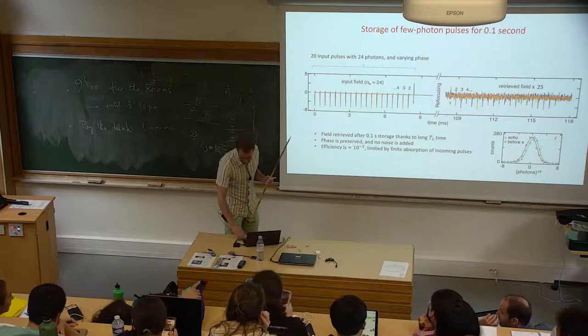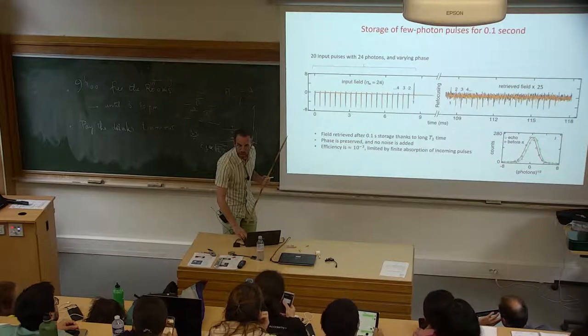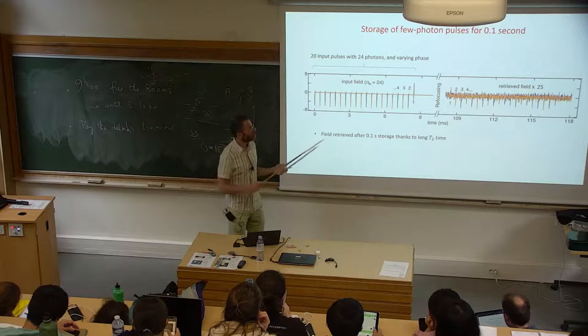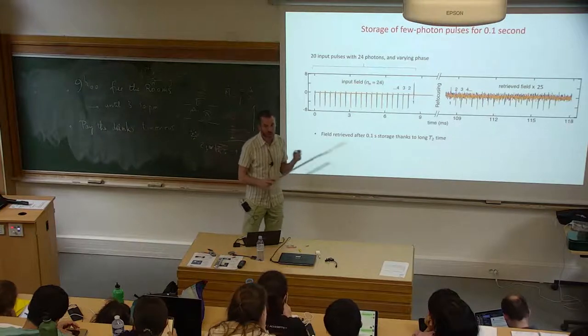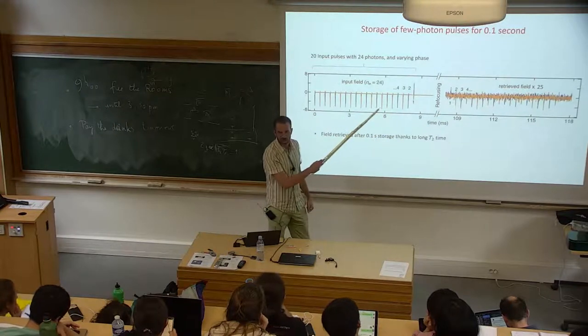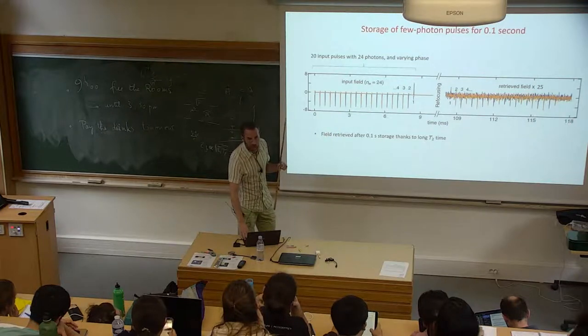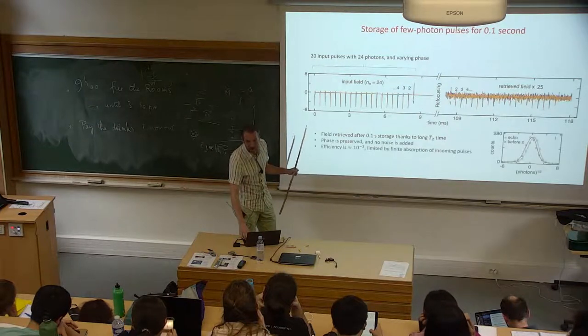Patrice? Oui. It seems like you're storing the information and then waiting until it decays to get it back, right? Basically, you're right. It's a memory, so we're doing nothing. Ideally, we would like to store it as long as possible, and yes, it has decayed. But in fact, the decay is not due to T2, because T2 is actually longer. You see that the amplitude here is still much smaller than here, but it is smaller not because of loss of coherence. It is smaller because the absorption was much lower in this experiment than in the previous one. This is really the limiting factor in this experiment.